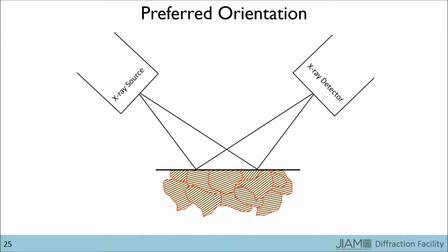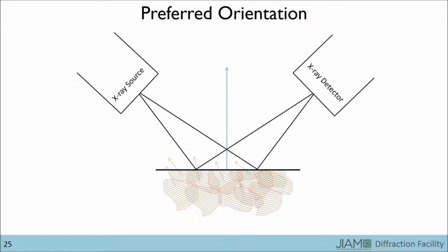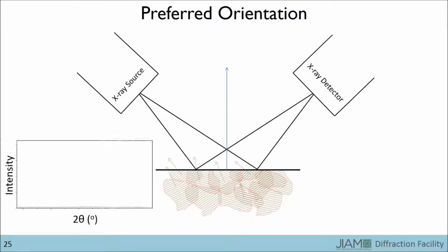Now let's look at a sample with preferred orientation. In this example, our diffraction vector is the same as before, but the 100 plane normals are different. For this sample, there is a clear preference for the 100 normals to point up and to the left. Because none of the normals are aligned with the diffraction vector, no grains will contribute to the diffraction peak, so only background will be visible for this atomic plane, even though the source and detector are at angles that should produce a diffraction peak.